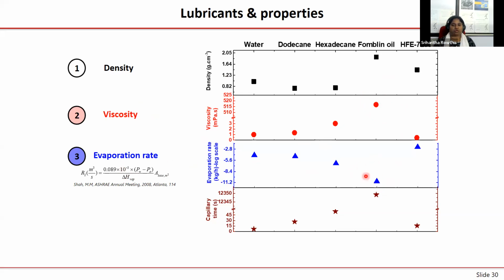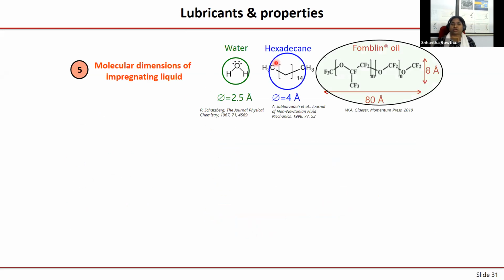Then evaporation rate. You don't want the liquid to be evaporating quickly. Then you also want the capillary time of the oil to be smaller. But in this case, it's a trade-off. Fomblin oil is not doing very well. We want the least capillary time so that the oil can replenish very quickly. Then we also have to see the dimensions. So water, hexadecane, Fomblin oil. If you look at the dimensions, Fomblin oil has a much bigger molecule. The higher the molecular sizes, again, the separation between the solid contacts is going to increase, and hence we are going to have lower friction coefficients. So in that way, again, Fomblin oil is good.